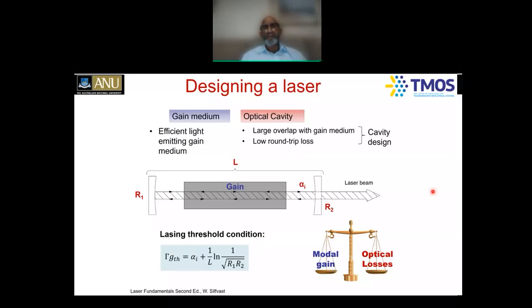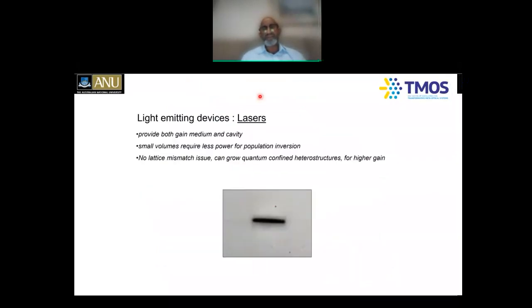So if you take a nanowire and excite it with a laser pulse, the nanowire acts like a waveguide because of the high refractive index of the nanowire with respect to the surrounding medium. And then both ends of the nanowire act like mirrors because of the refractive index difference again. Also, these nanowires are made out of III-V semiconductors like gallium arsenide and indium phosphide. They also have gain. So that means you can see now suddenly, I don't have to do anything. If I design my nanowires right, each nanowire in principle should act like a laser.